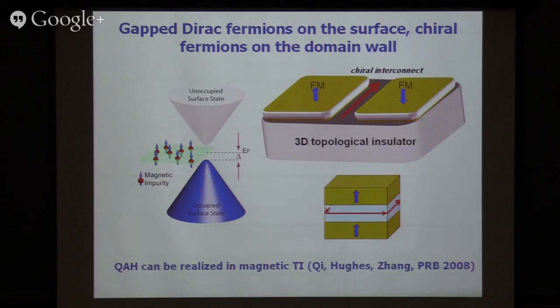And the chirality is defined by the vector cross product between the surface normal and the gradient of the magnetization. By the right-handed rule, if you point your finger to the surface normal and thumb to the gradient of the magnetization, your finger will point to a unique direction along the domain wall where the current can flow. So this is a chiral current. Even if you break the symmetry slightly on the surface, it will lead to this chiral state. So that leads to another interesting state of matter called quantum anomalous Hall state.